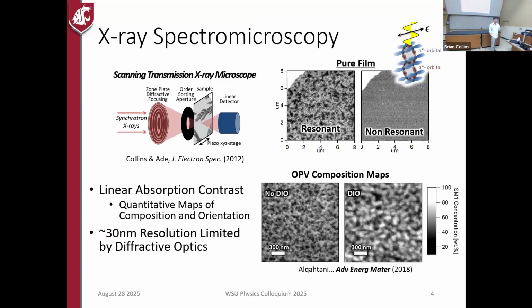So we can then take this spectroscopy measurement and pair it with a bunch of different nanoprobes. This is scanning transmission X-ray microscopy, which we've been developing at the ALS. You come in with these X-rays, you diffractively focus them to a spot, they transmit through your thin film sample into a photomultiplier tube or something. And then you raster that across to get a map or an image of your material. This is a non-resonant X-ray microscope image of a thin pure polymer film. And you can see the edge of the film there where there's no film and then nothing happening.